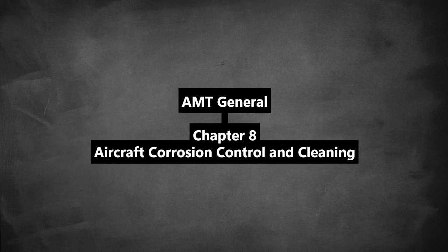Now, aluminum. The most common material, but it has its issues, right? Forms that oxide film, but vulnerable to galvanic corrosion. Exactly. And the oxide film is good, but easily damaged. And aluminum is quite active, so it loses out in galvanic couples with many metals. Prone to pitting, intergranular corrosion, stress corrosion cracking, depending on the alloy and conditions.